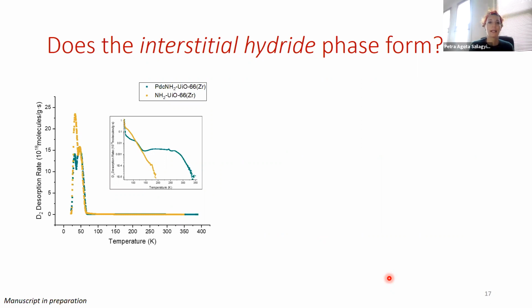The way we looked at it is, we used thermodesorption spectroscopy. We actually used deuterium, but it doesn't really matter. So we loaded the empty framework and the palladium-laden framework separately with 100 millibars of deuterium at room temperature, allowed a half-an-hour equilibration, and then quenched the sample temperature to 4K, at which point the hydrogen should occupy all adsorption and absorption sites. After that, we pump away all the hydrogen that's not been adsorbed or absorbed in the system, and we start to linearly increase the temperature, and we have a mass spectrometer attached to this, so we can see the evolving deuterium as it's being desorbed from the framework.